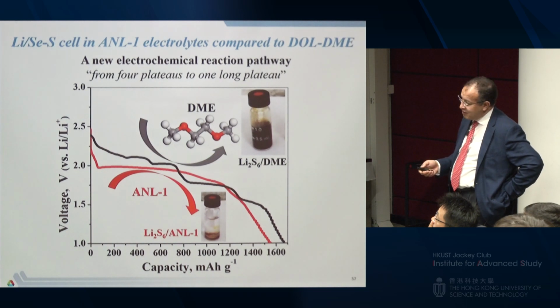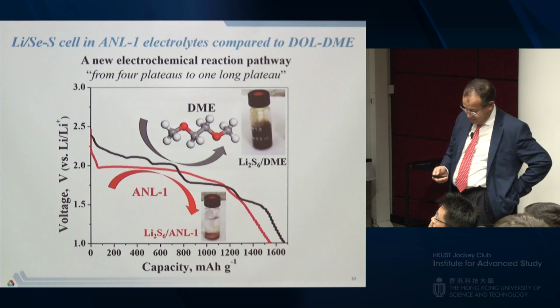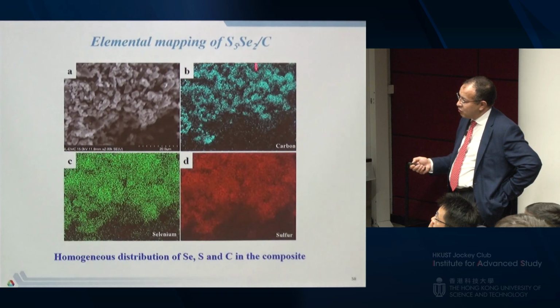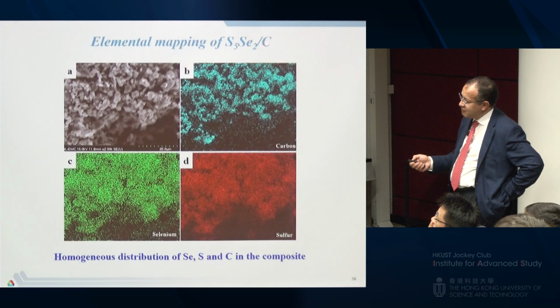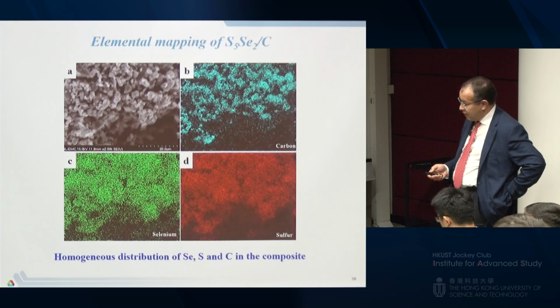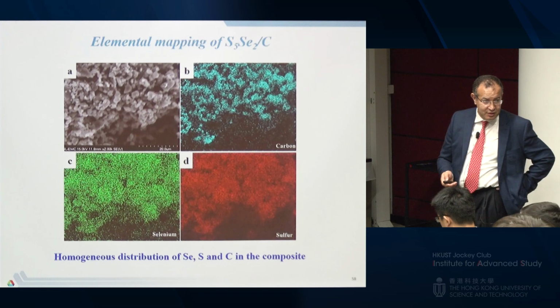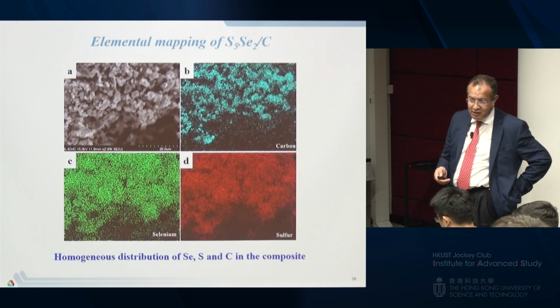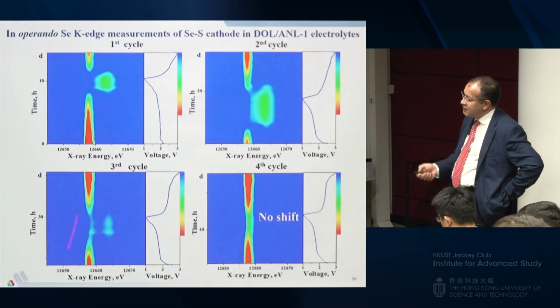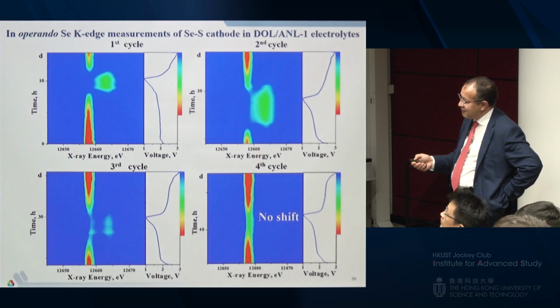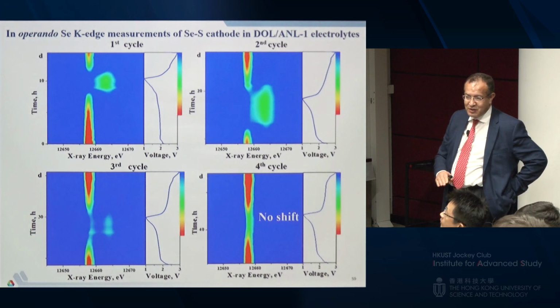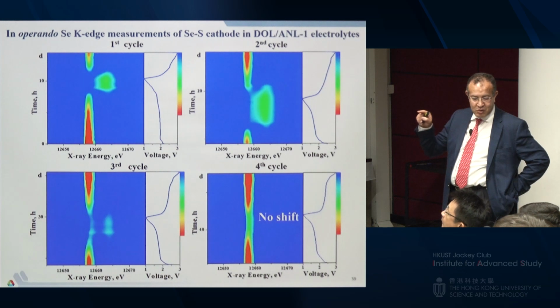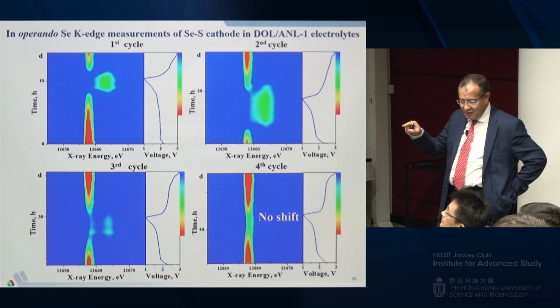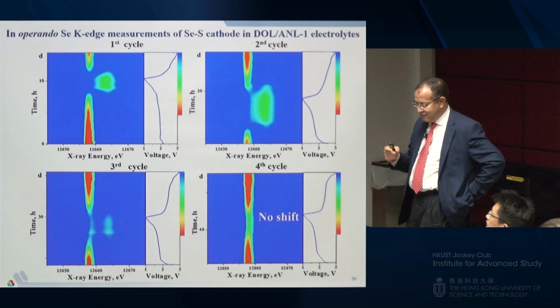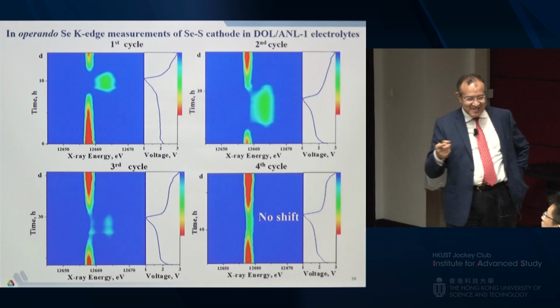So now we need to know if this material works. And so we incorporated carbon. We put about 10% of carbon in this system, so you can see the dispersion of carbon. But we don't put 50 or 60%, just 10% like in a lithium-ion configuration. We ran the XANES and it is very flat, so we don't have any shift, which means there is no dissolution. This is the most important experiment because with the naked eye, there might be some dissolution.